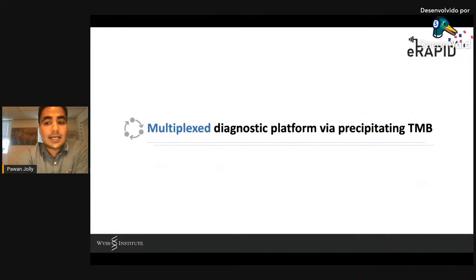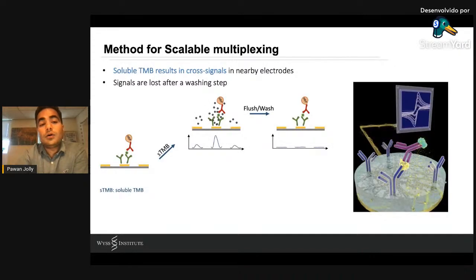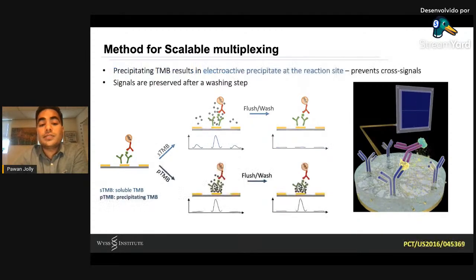So as our topic was multiplex diagnostics, this was the other aspect of how we can actually perform multiplex diagnostic, which is specific as well as sensitive. So, we are using an electrochemical ELISA, and just to give a little bit of background, usually people use soluble TMB. TMB is basically a substrate for enzyme, in this case it's HRP. So if you use soluble TMB, what happens is that the signal is then produced in the solution. The enzyme catalyzes the TMB, electrons are produced in the solution. So if you have neighboring electrodes, the neighboring electrodes can pick up the signal. And if you flush these sensors, you actually lose all the signal because the electrons are produced in the solution. What we are using is a precipitating TMB.